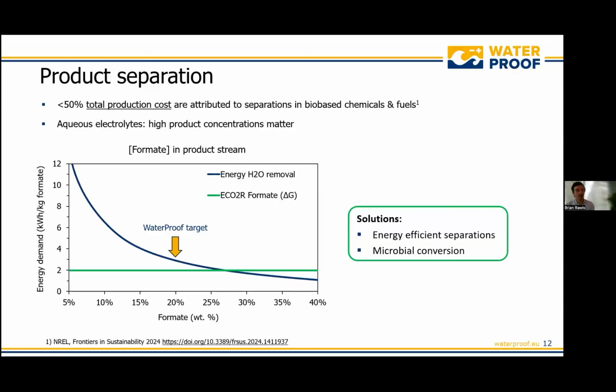Another very important aspect of CO2 reduction is the product separation. I alluded to this before in my presentation, but just an interesting fact that I found in literature is that one report said that approximately 50% of total production cost is attributed to the separations in bio-based chemicals and fuels. So it's an incredibly important topic that does not get as much attention as needed, especially if you're producing a liquid soluble product, as we are, making potassium formate and formic acid. So those high product concentrations are very important.